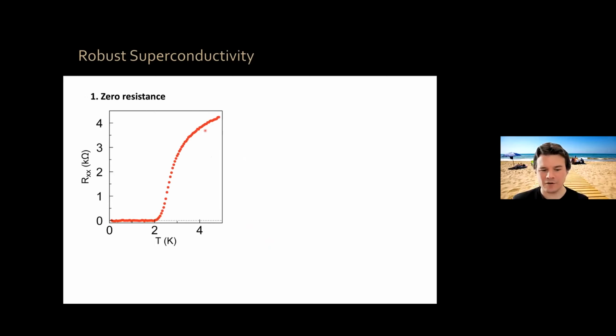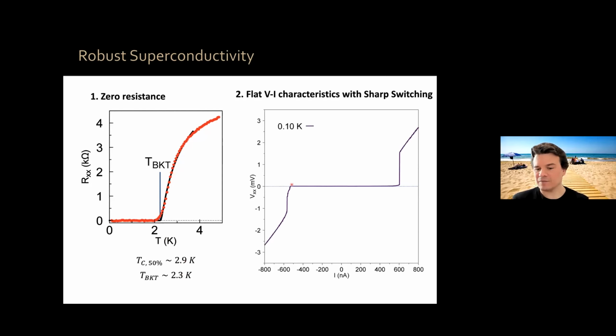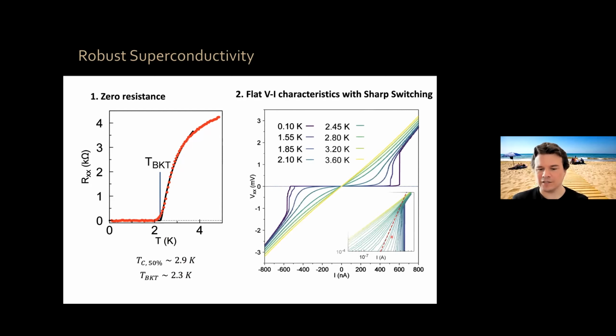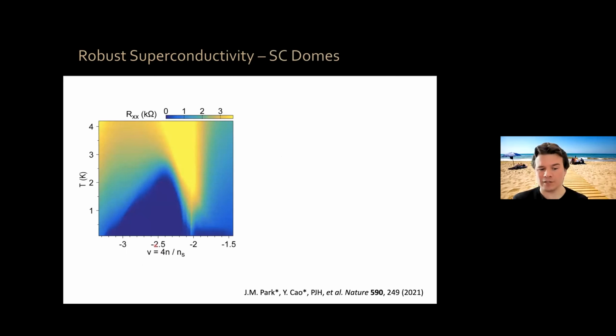You have zero resistance in the resistance versus temperature curves. You can determine the Berezinskii-Kosterlitz-Thouless transition temperature, which is about 2.3 Kelvin for this device. The TC 50% is about 2.9 Kelvin. The system has flat voltage-current characteristics with sharp switching. You can do temperature dependence. You can look at the BKT physics from this type of plots. You get the same TBKT. As I mentioned, it's an electrically tunable superconductor.